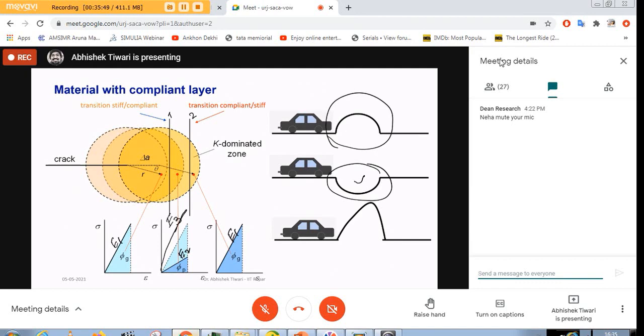And we can also design it in a way that it is not so symmetric. So we can create this situation also by changing the interlayer dimensions. So we can do something like this, or we can change the interlayer in whatever way we want. And that will affect the crack driving force, how it increases and decreases. Using this idea, which we call material inhomogeneity, we think that we can increase the crack resistance, because I'm not changing anything in the car and I'm just changing the road construction, and I'm able to change the velocity.